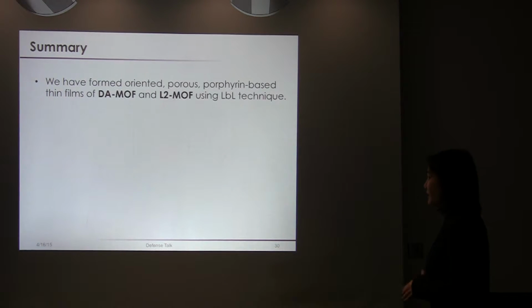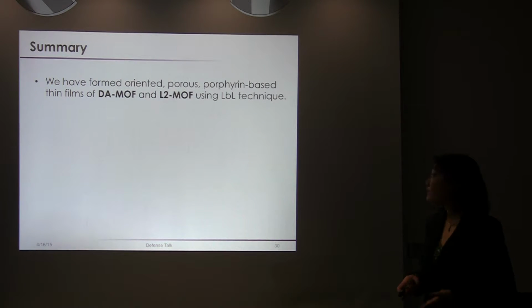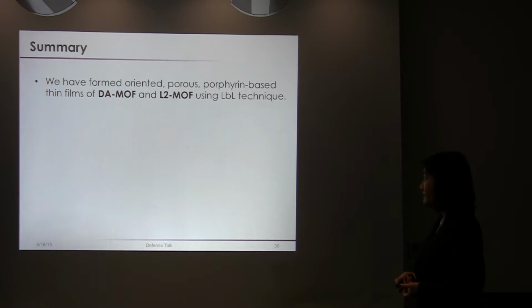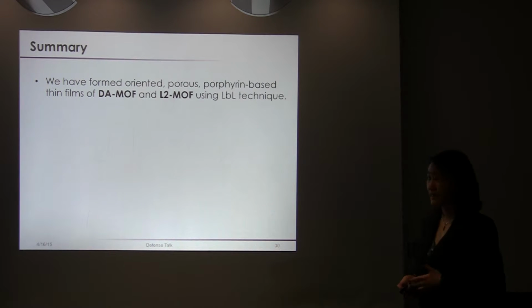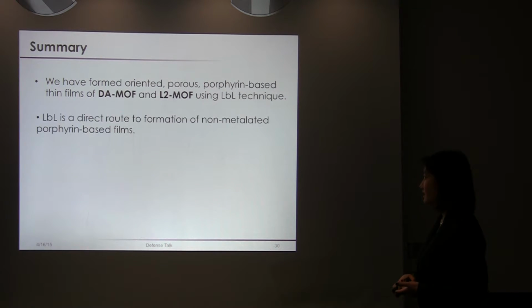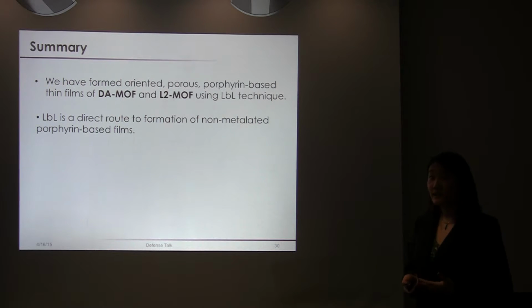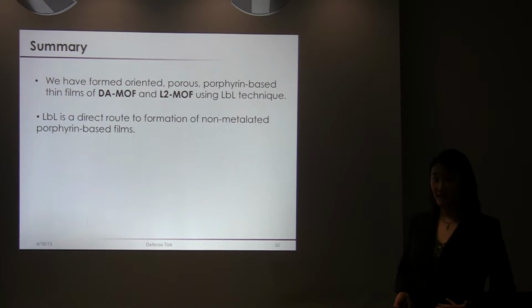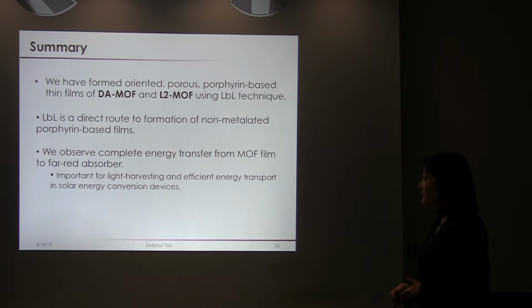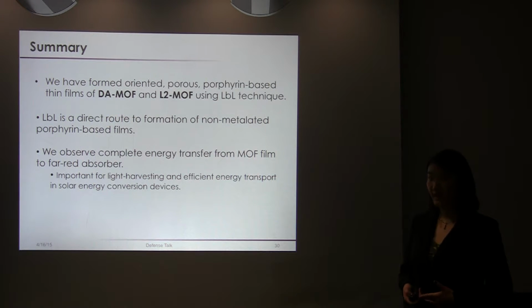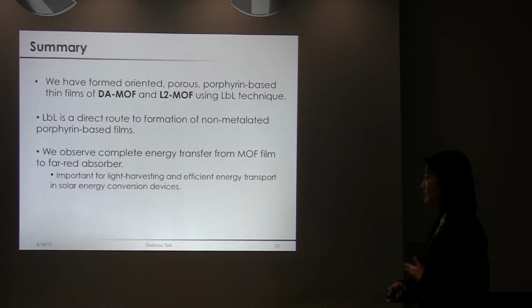So in summary, what I've shown is that we have formed oriented porous porphyrin-based thin films of DA MOF and L2 MOF using this LBL technique. And layer by layer is definitely a direct route to forming non-metallated porphyrin-based films. And thirdly, and most importantly, we observe complete energy transfer from the MOF film to the far red absorbing dye. And these are important findings especially for light harvesting and efficient energy transport behavior for solar energy conversion devices.